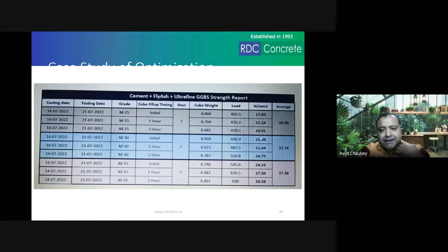Now, this is another case study from Gujarat, where they have used ultrafine GGBS along with the cement and fly ash, and they did this for reducing their cost of concrete. So if you see M25, M30, and M35, this was a research work also. They filled the cubes initially. They filled cubes after 1 hour. They filled cubes after 2 hours, and they did the same thing for all the other grades. So if you see, the strength that they get is higher for later age in all the cases. Initial concrete strength is much lesser.